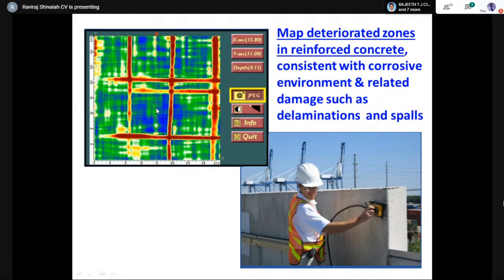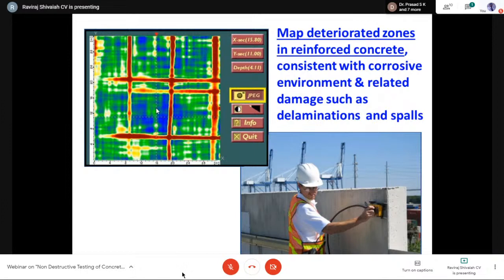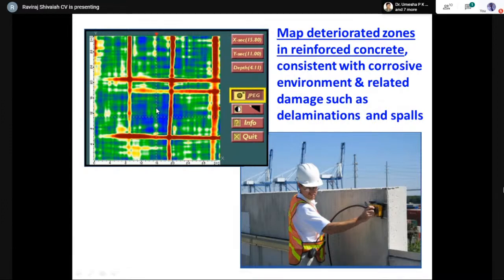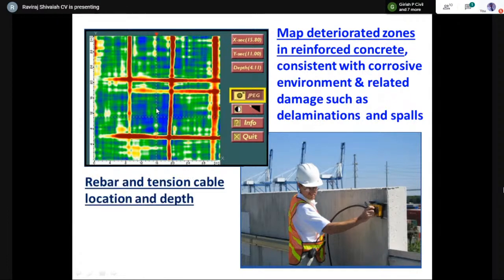So what we are trying to talk about is that nowadays the technology is progressing to such an extent that you can get very good detailed information about the concrete. The only thing is, as I told you, they are very expensive and it has to be done only at those places where it necessitates us to do these kinds of tests. However, they are available, where you can map deteriorated zones in reinforced concrete, consistent with corrosive environment and related damage like spalling and delamination.